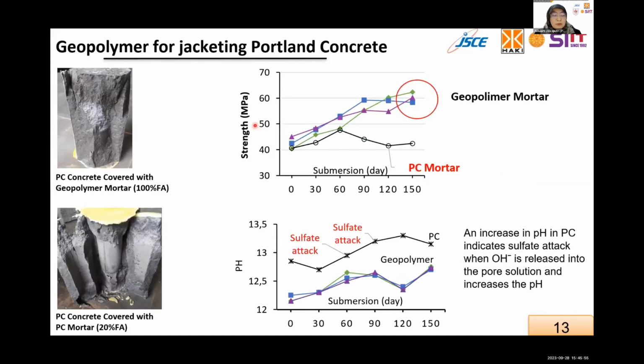It may guarantee a dense and stronger interlayer continuously. And then when we test the bond strength, the bond strength of geopolymer mortar is much better than that of PC mortar here. We are aware that a cover thickness of 5 centimeter is suitable for the inner concrete. So the thickness is 5 centimeter.